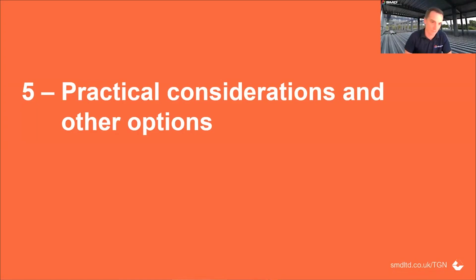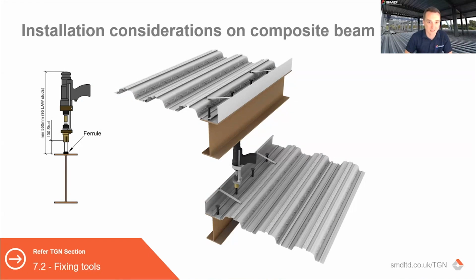This is just the last couple of slides now to finish off. A couple of practical considerations. So you saw the gun at the start. The gun has obviously got a minimum size, and the stud has a minimum length. So you need to make sure, if you're designing composite beams, that you can get those studs on site. If you've got a beam over a beam, like in this scenario, you need at least 550 millimeters for a 95 length after weld stud to enable that to physically be put on. There are other ways of putting studs onto top flanges, not using the stud welding gun process, but that will be a bit of a pain. So the better situation in that scenario is to design the bottom beam as non-composite or pre-studded in the works, or find a different way of providing those studs, if the dimension is quite tight between the underside of the top beam and the top of the bottom beam.